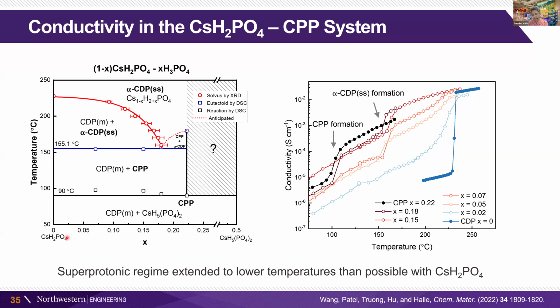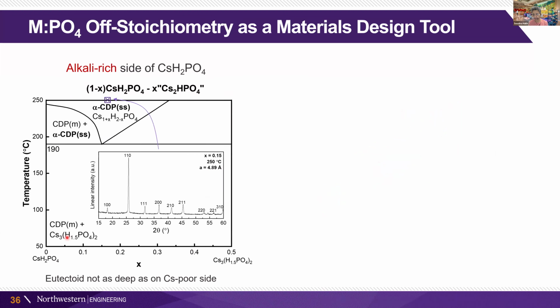And the conductivity in this case is attractive. So we see that this is linear temperature, not an Arrhenius plot, we can see that when the CPP compound forms, we have a small jump in conductivity. And then when we go to the solid solution phase, we have another higher temperature jump. That's at the eutectoid temperature of 150. And we get a much wider range of high conductivity behavior that we can utilize and exploit in our materials.